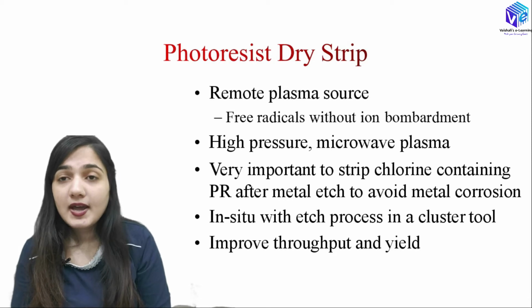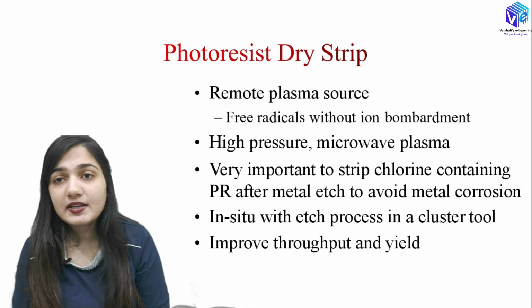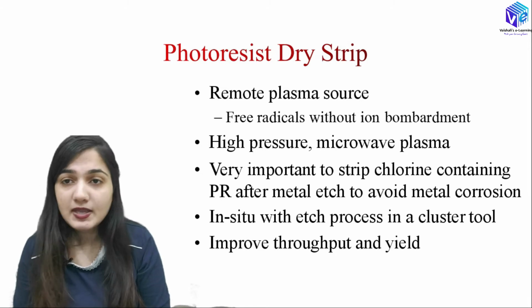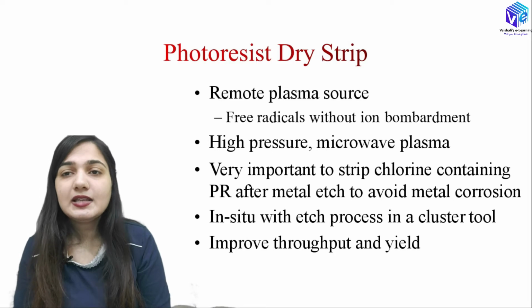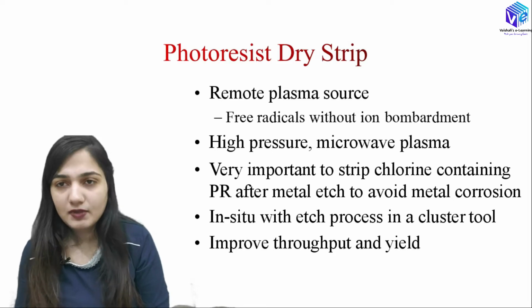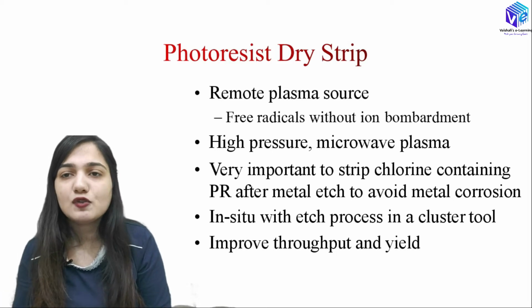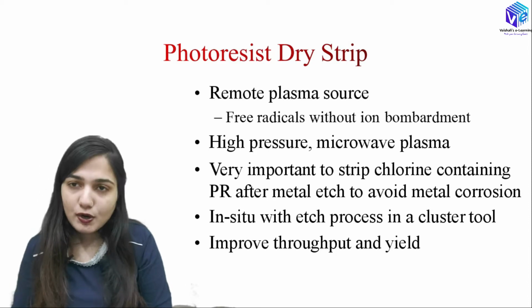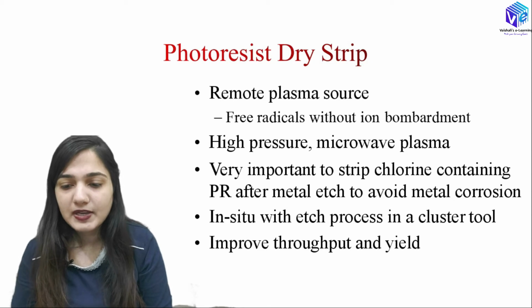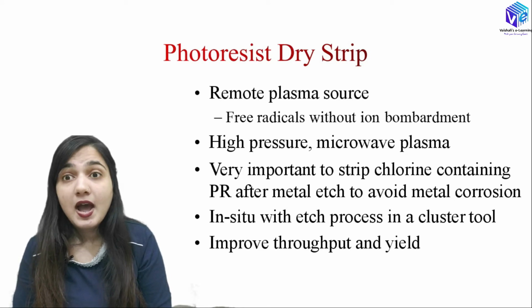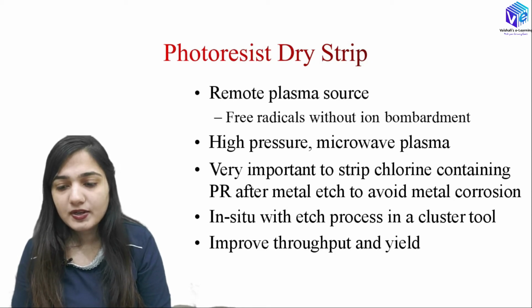Here I will be using a remote plasma source which is generating free radicals only. It is not giving any ion bombardment, so the system will be devoid of ion bombardment. It will be generating some free radicals. These free radicals will be reacting with the photoresist and dissolving out the photoresist layer. We will see in detail the various reactions that are happening. It is a high pressure system, and I am using microwave plasma over here.